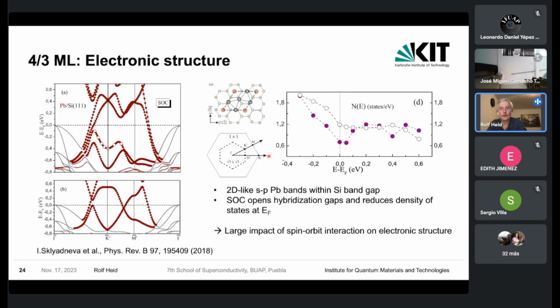Now here are shown some of the theoretical results we have obtained. On the left-hand side, you see a calculation of the electronic structure of this so-called 4/3 monolayer structure, and we have been focusing on this type. You see here the top valence band of the silicon, and the conduction band is somewhat up here. And in this semiconducting gap of silicon, you see a variety of electronic bands coming from the lead, which renders essentially this surface layer metallic.